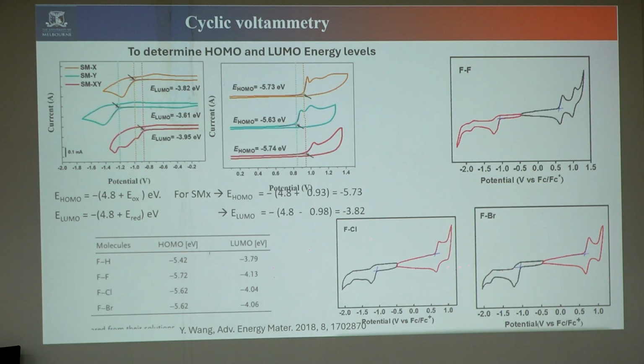This is an example I am giving here, also calculated. For any organic compound, there should be one oxidation potential and one reduction potential, because we are designing the material like that. But for some highly N-type materials like PCBM, if you have multiple electron reductions, one or two electrons, you may not see that. In that case, you define the LUMO level first, and by using the band gap you can find out the HOMO level. That's fine. Since you know, I will skip to the next one.